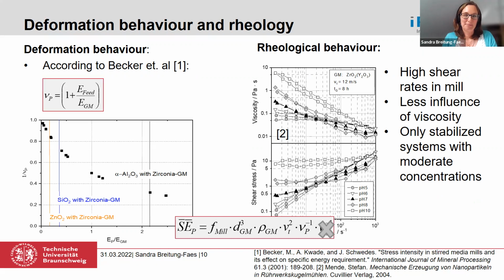It is the viscosity. Here, I thought, okay, if you've got high viscosity, you also have some reduction of the grinding bead velocity itself. But at least I looked at all the experiments I had available, and later on I decided not to take this into account. And here I would like to show you the viscosity over the shear rate on the x-axis. What you see here are experiments for alumina grinding in the nanometer range.